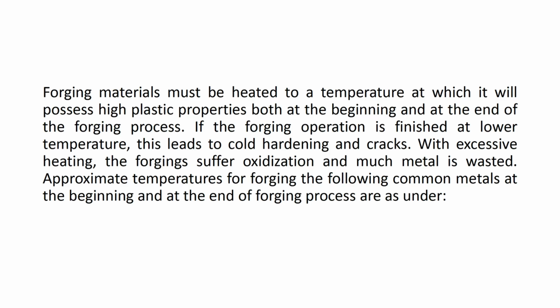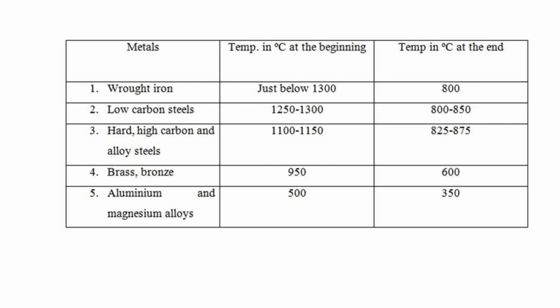The approximate temperatures for forging common metals are presented in a table. Let's read it clearly. For wrought iron, the temperature at the beginning is just below 1300 degrees Celsius and at the end, it's 800 degrees. For low carbon steels, it's 1250 to 1300 degrees at the start and 800 to 850 at the end. For hard high carbon and alloy steels, it's 1100 to 1150 degrees at the beginning and 825 to 875 at the end.